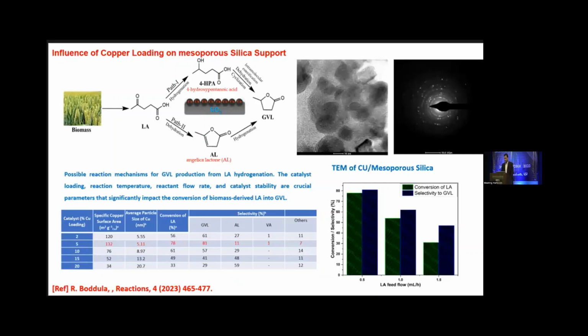So also we explore a different support, mesoporous silica, and this is the TEM image of the copper supported on mesoporous silica, and this diffraction pattern is showing high crystallinity. And there are two routes or two paths, and both have different byproducts. For the first path, it can form hydroxypentanoic acid, and for the second path, it can form γ-valerolactone, and both can lead to the formation of GVL.